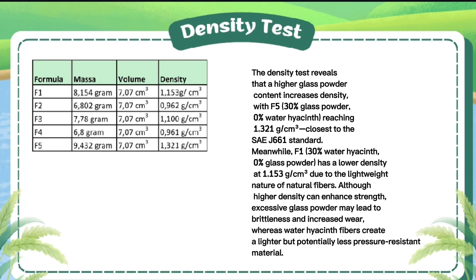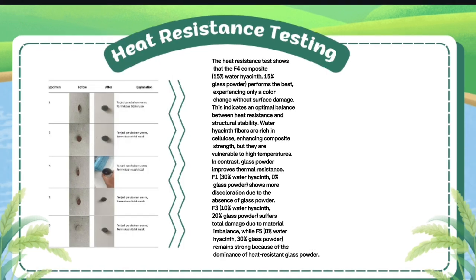Although higher density can enhance strength, excessive glass powder may lead to brittleness and increased wear, whereas water hyacinth fiber creates a lighter but potentially less pressure-resistant material. Heat resistance test. The heat resistance test shows that the F4 composite, 15% water hyacinth and 15% glass powder, performs the best, experiencing only a color change without surface damage. This indicates an optimal balance between heat resistance and structural stability.